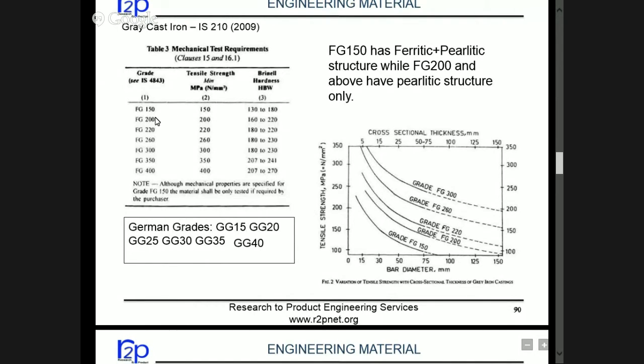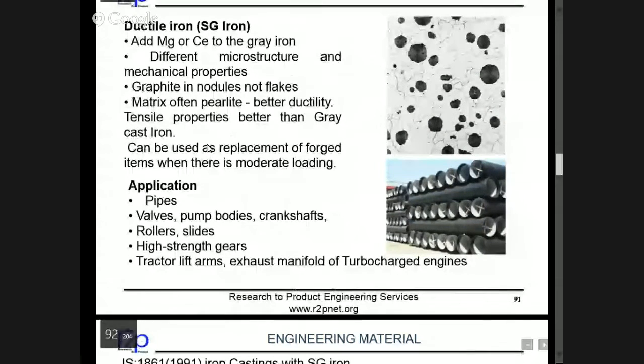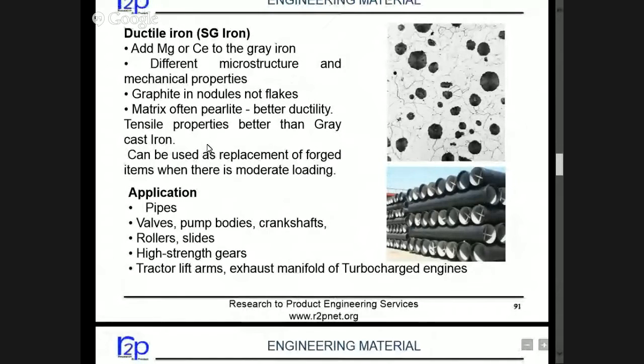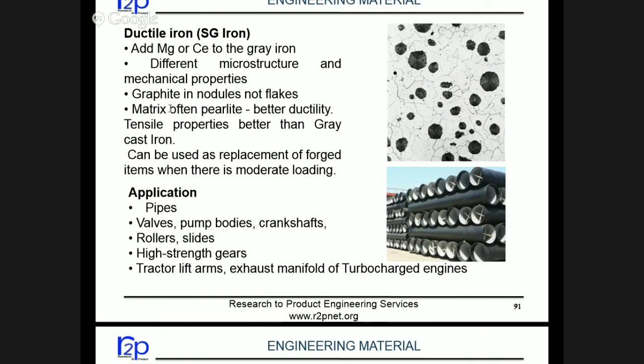And as I told you, again I'm mentioning that for FG260, 260 is its tensile strength. So the higher the number, the higher the tensile property. Now the other popular cast iron is SG iron, spheroidal graphite iron. While making this, magnesium and cerium are added so that the carbon flakes do not appear, but the graphite appears in spherical form, right? So it acts as a barrier and the tensile strength improves. Wherever the requirement is higher tensile strength, there we go for SG iron. And of course it's expensive.